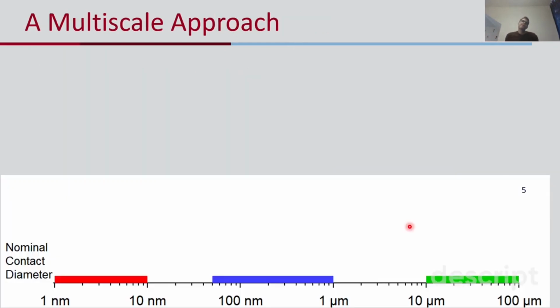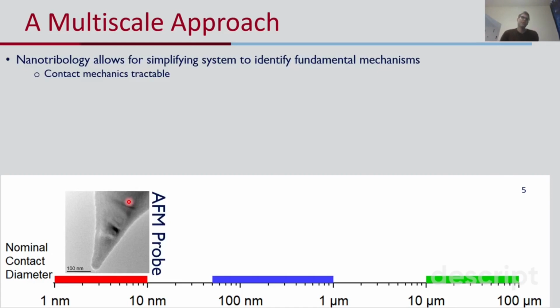My way of trying to understand the response of these materials is a multiscale one, looking at different length scale contact diameters. So at the smallest length scale with contact diameters below 10 nanometers is what we refer to as nanotribology, where we take a very sharp AFM probe with a radius at the tip that we can characterize quite well and slide that against the material of interest. And this is really useful because the fact that we have a well-characterized single asperity means we can apply standard contact mechanics to understand what's going on. So we can learn things like what the real area of contact at a particular load is.